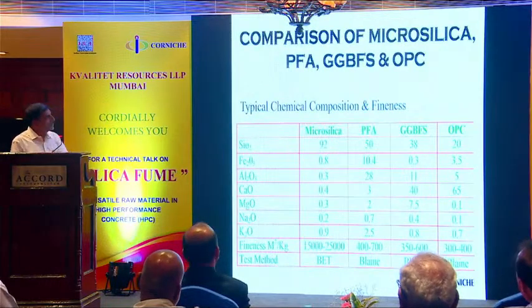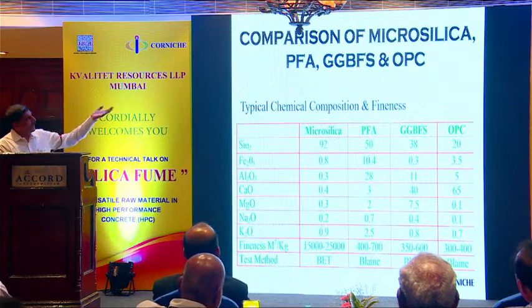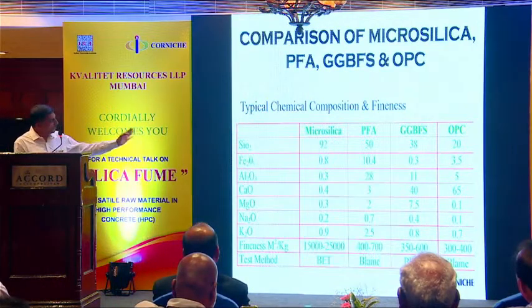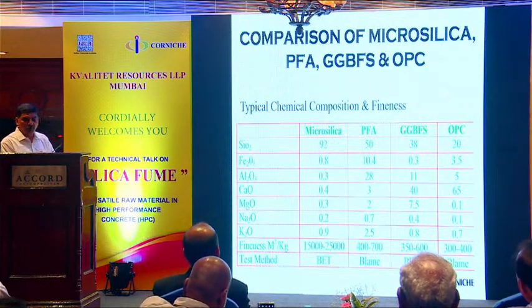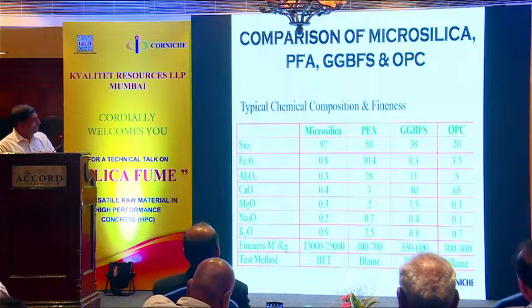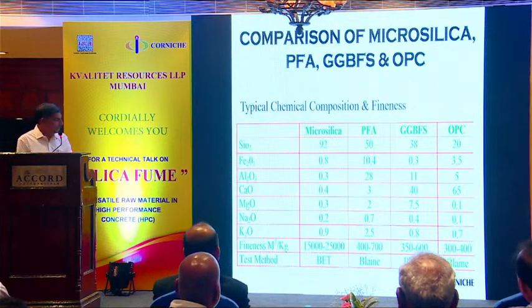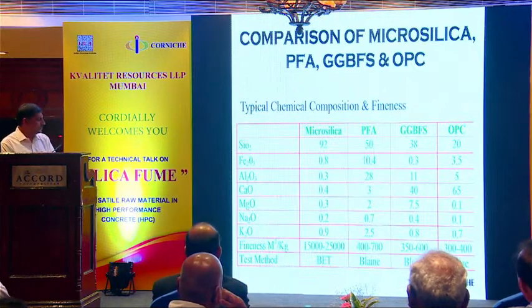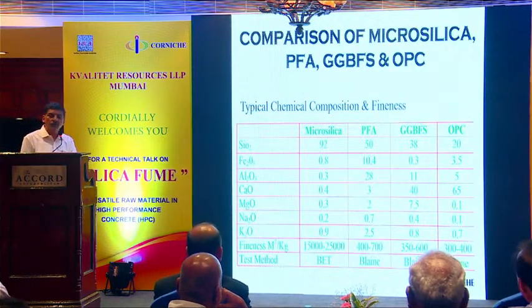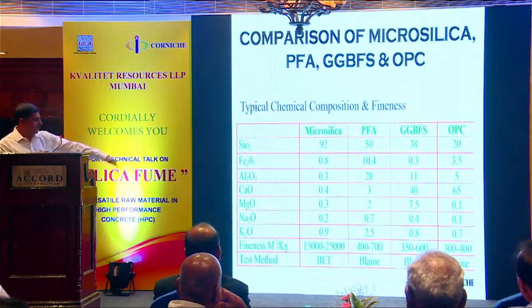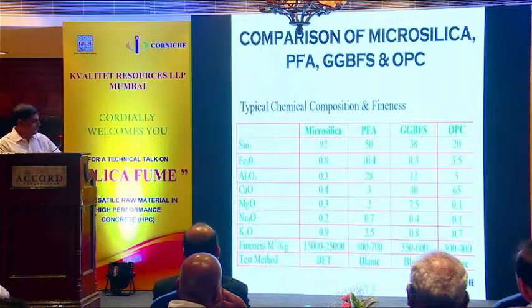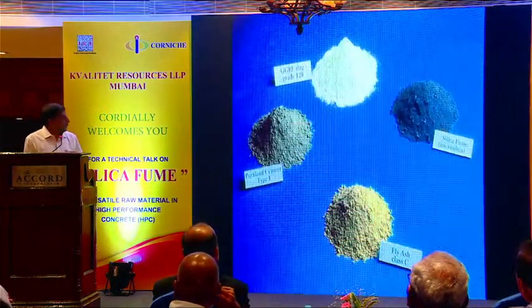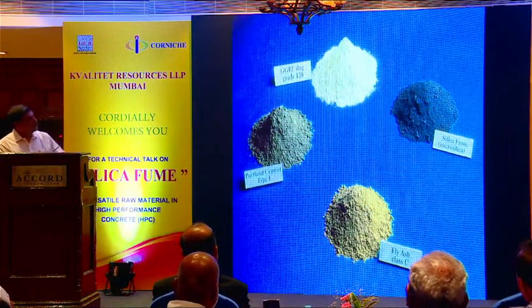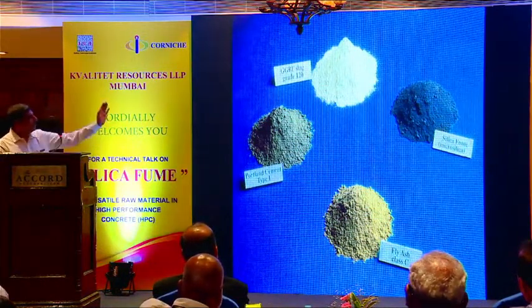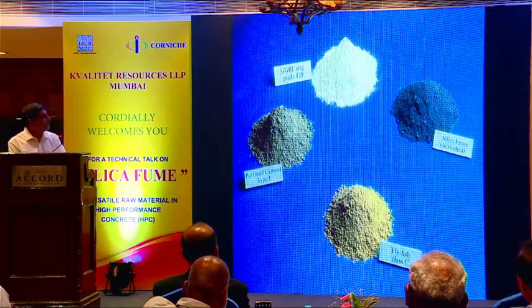So I've tried comparing silica fume with fly ash, slag, and OPC. It stands out on two things. It's highly siliceous as compared to the other three. And see the fineness: while the other three fall between 300 and 700, silica fume is minimum 15,000 to 25,000 meters square per kg. The other three are measured with Blaine, and here we use BET, the nitrogen absorption method. How do the materials look? Silica fume on the far end there, then GGBS, OPC, fly ash.